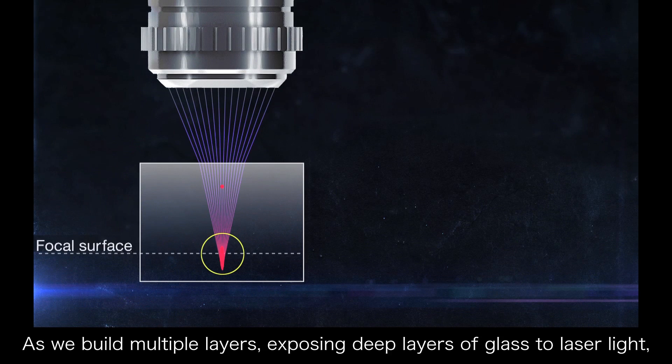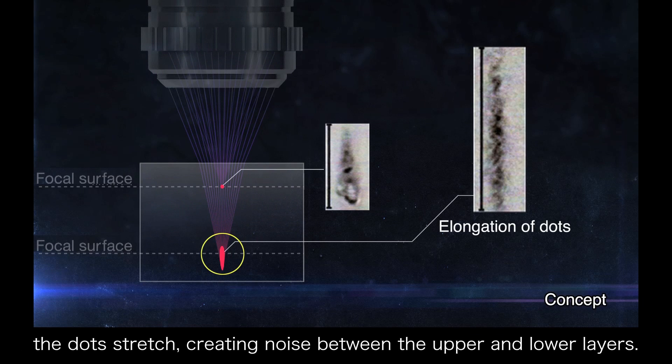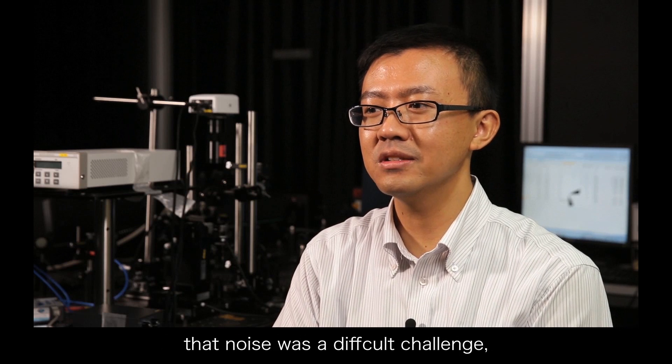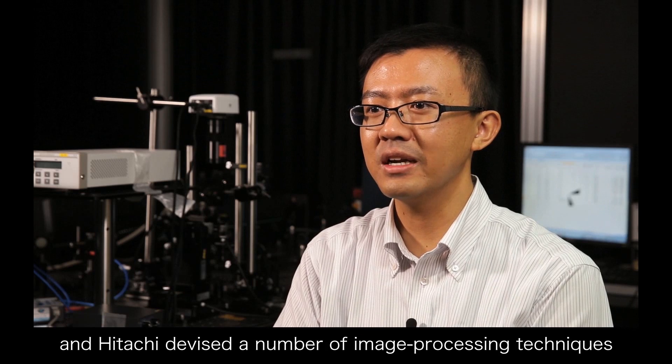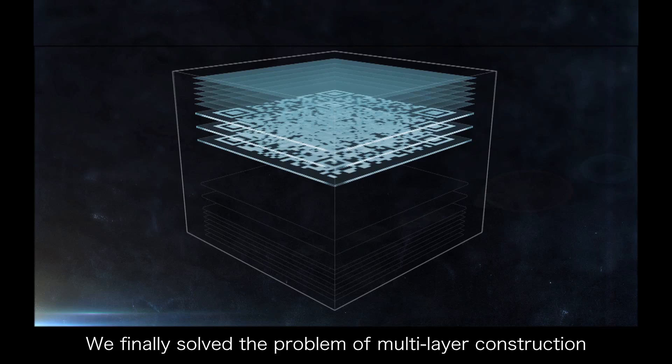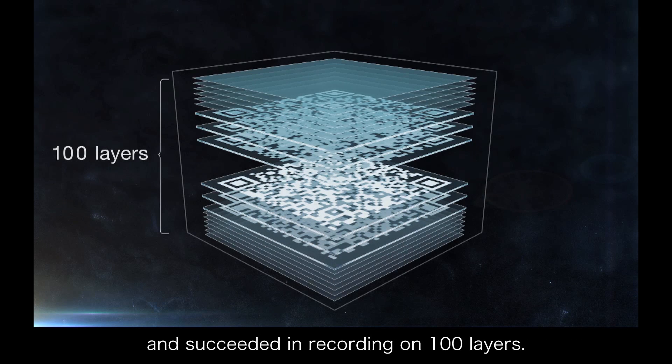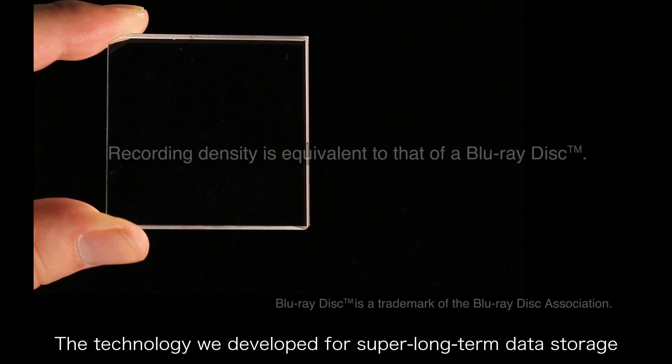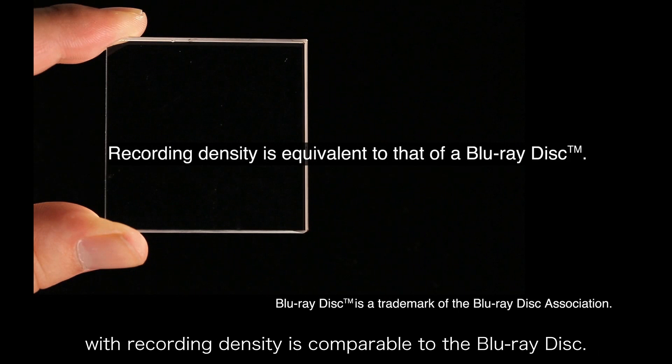As we build multiple layers, exposing deep layers of glass to laser light, the dots stretch, creating noise between the upper and lower layers. We finally solved the problem of multi-layer construction and succeeded in recording on 100 layers. The technology we developed for super long-term data storage with recording density is comparable to the Blu-ray disc.